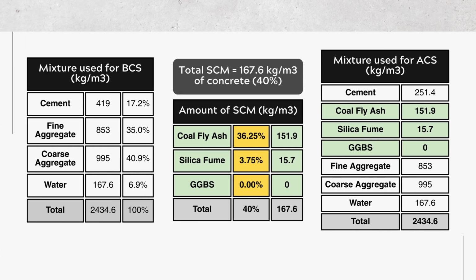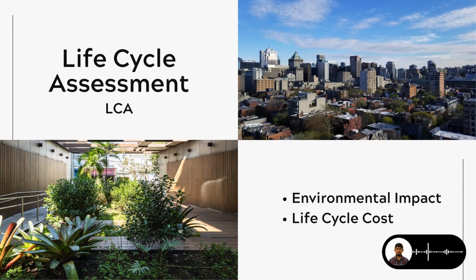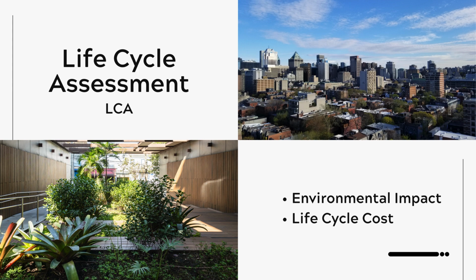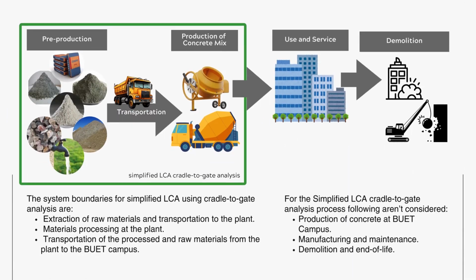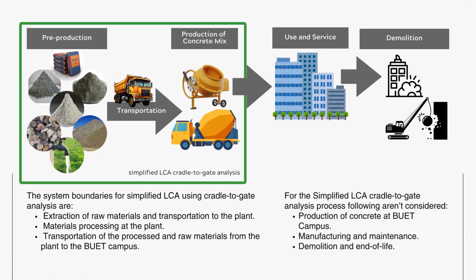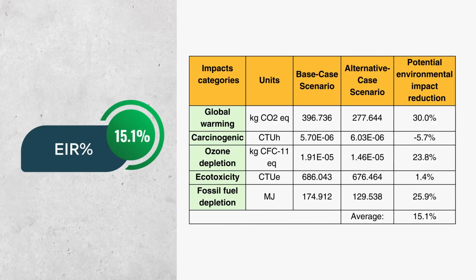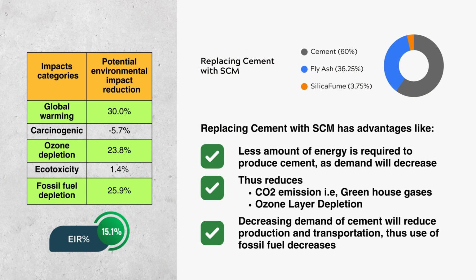Using this optimized mix ratio, we calculated each element of our ACS mixture. Our optimized mix achieves a 15.1% overall environmental impact reduction. Notably, we reduced global warming potential by 30%, ozone depletion by 23.8%, and fossil fuel use by 25.9%. Reductions in global warming and fossil fuel depletion are a direct result of lower cement use and optimized transportation.